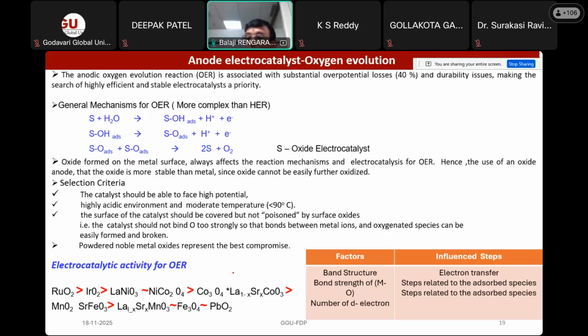But when you go with such metal oxide based electrode materials, what will happen? Metal oxides normally have a poor electronic conductivity when compared with metals. So obviously it has some resistance. So the selected metal oxide should have high electronic conductivity, on par with the metal. In that case, ruthenium oxide and iridium oxide will meet the electrical conductivity requirement on par with the metal. That's why ruthenium oxide and iridium oxide based materials have been used as the oxygen evolution electrocatalyst for water electrolysis.